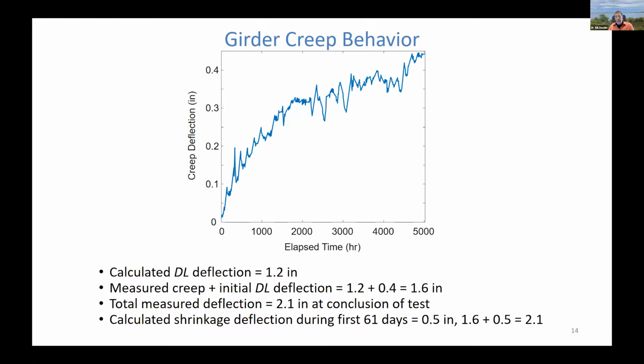And the calculated dead load deflection for this particular beam is 1.2 inches. So the creep deflection we measured was only about 0.4. So the total creep and dead load is 1.6. So that is actually very encouraging because the creep deflection we measured is about 1/3 of our initial dead load. However, our total measured deflection at the end of the test was not 1.6, it was actually 2.1.